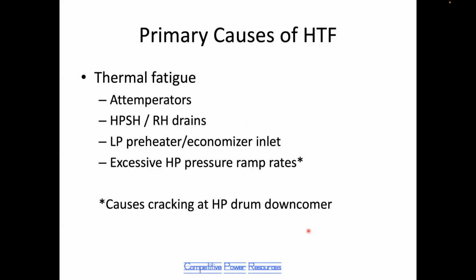So the primary cause of tube failure, as I said, is thermal fatigue. Thermal fatigue generally manifests itself at attemperators, HP superheater and reheater drains, to a lesser extent, LP preheater and economizer inlet sections, and excessive high pressure drum ramp rates causing cracking in the drum.